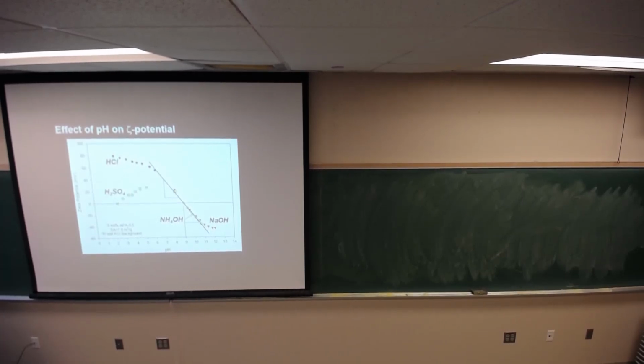Let me change the question. Let me fill in the question a little more. What would that imply in terms of the rheology response of this suspension? It behaves the same way either way. You would expect the viscosity to drop as you move away from the isoelectric point, regardless of direction. Does that make sense? So if you push the pH up, you would expect the viscosity to decrease at the same rate that you would see the viscosity decrease if you push the pH down.